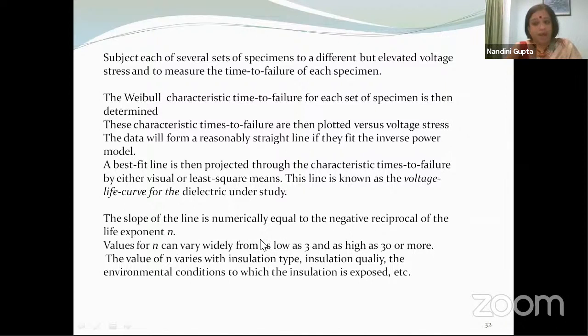Generally, n can vary widely. I say that often the value 7 is taken, but it has been known that people have taken values as low as 3 or as high as 30. The value of n will depend upon the material, the insulation system, and many other factors, many other operating conditions. So it is very difficult to predict beforehand what value you can choose, but the value of n can vary